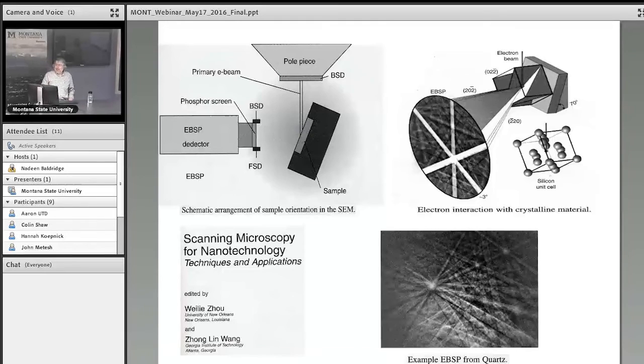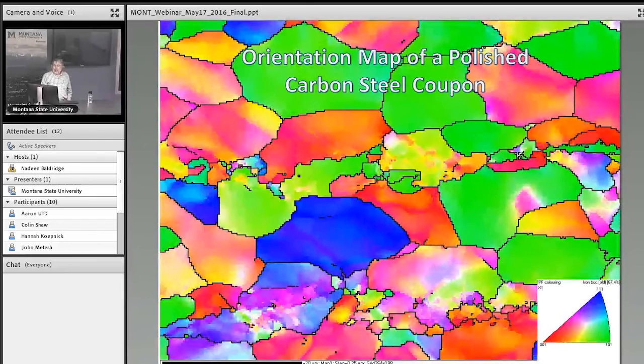And they are very mature technology. Within milliseconds, we can interpret. We can tell the orientation of your crystal. We can tell whether it's strained or not. We can also tell its phase within a submicron area, sometimes even smaller. And here it is. We just mapped a nicely polished iron surface. Here, blue areas are 111 orientation. Green ones are 101 orientation, red ones are 100 orientation.